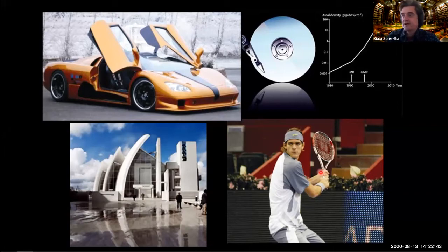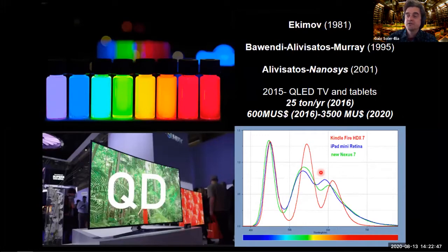To give you a very fast idea of the time between the development of an idea and the market, this is a very interesting case. These luminescent flasks you see here are a material called quantum dots. These quantum dots are small nanoparticles. They are transparent because they're very small and don't scatter light. Once illuminated with UV or blue light, they can re-emit light, luminescing in several different colors. This emission is different not because the material is different, but because the size of the particles is different. Larger particles emit light in the red. Smaller particles emit in the purple or blue. So this is very nice.